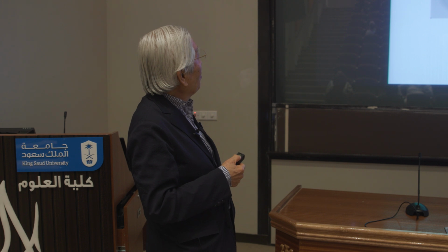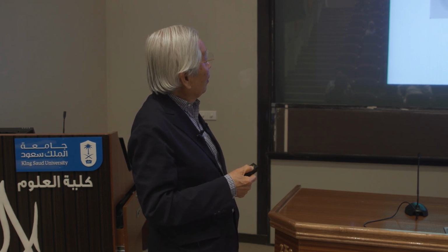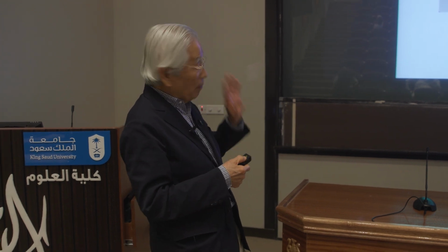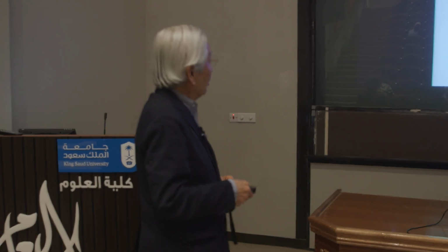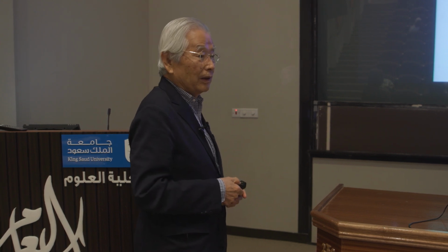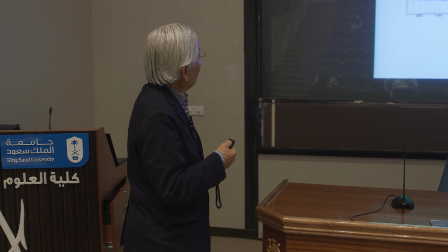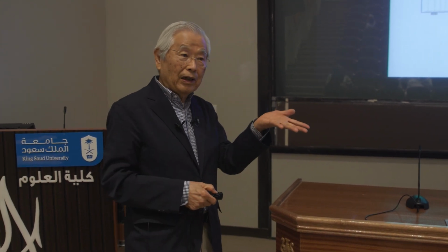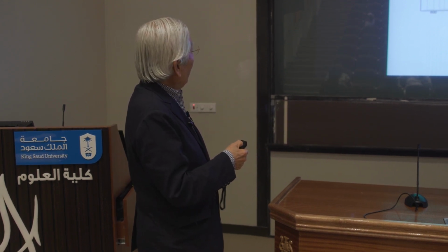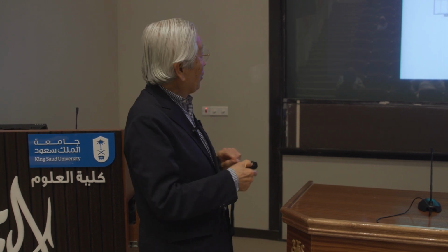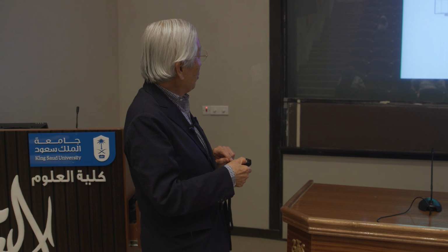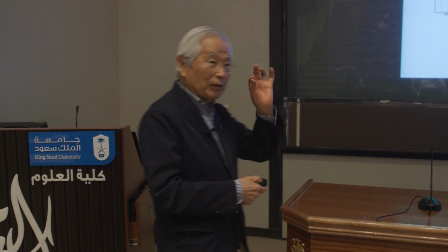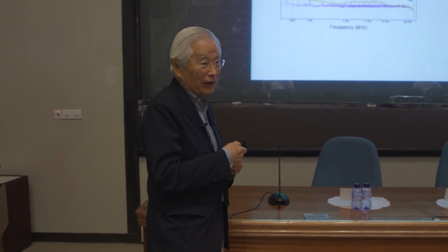So next one is the minimum weight of CNT and 30 nanometer gold nanoparticle. This is not carbon, but gold. You can utilize this technique for anything. I collected the amount on these papers. All right. So then these are the materials, but still we have some signal from the supporting paper itself. So this is 8 nanogram this time. Okay, very small amount, but still I can hear some sound. And then this one is much more. So in this way, the minimum amount of detectable sound is something like that, nanogram scale.